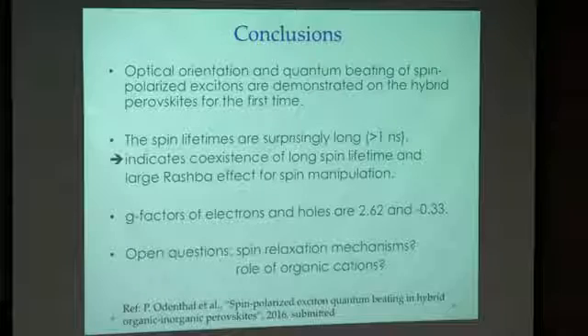And hopefully you still remember the question I brought up at the beginning of the presentation. So this material, probably because of the intrinsic band structure, we kind of get over that limitation that both spin lifetime and Rashba effect depend on the strength of spin-orbit coupling. Here we have both. The g factor of electrons and holes are first time determined explicitly to be 2.6 and negative 0.3.